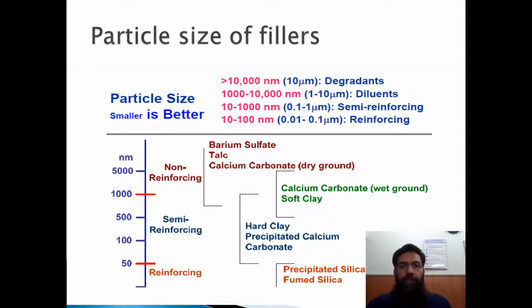Particle size of the filler is very important in terms of the selection of the filler for different applications. We have the different classifications of the filler, just like the non-reinforcing, semi-reinforcing, and the reinforcing filler. Mostly this classification is based on the size of the filler. The fillers which are in the nanometer sizes from 0 to 100 nanometer are mainly classified as the reinforcing filler, and silica and carbon black are the two main fillers which are used in our local automotive industry as the nano fillers.